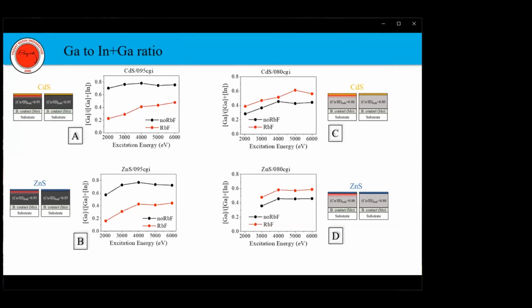Comparing figures C and D, a reversed effect of RbF PDT on the gallium concentration can be observed. This is again something directly related to the type of the absorber surface. In terms of the absorber buffer interface, there is almost no difference.